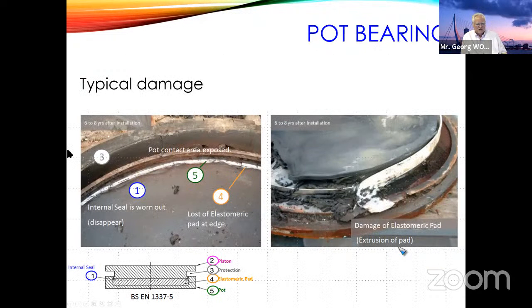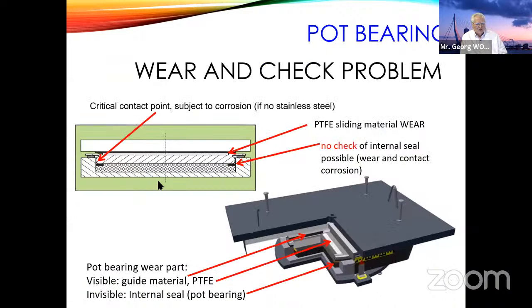These are some typical pictures here. You see this surface here, it should be sliding. It should be like the inside of a hydraulic cylinder, a very smooth and corrosion-free surface. But when you have corrosion and it's moving, then this surface gets rough, and it's really destroying the elastomer pad inside. These are the critical points here, this contact surface and the seal below. Of course, when you have a high quality seal, it will take much longer until you get the problem.